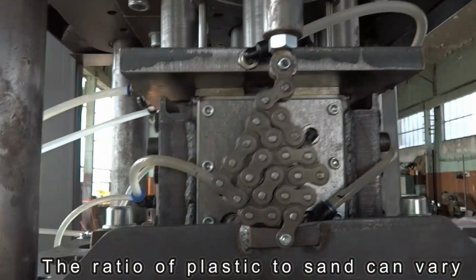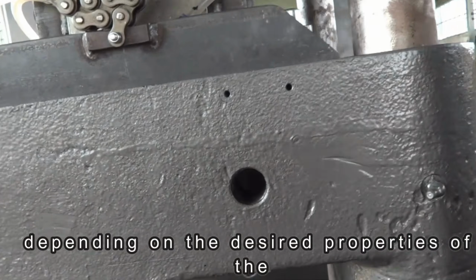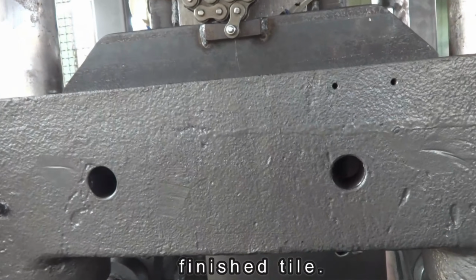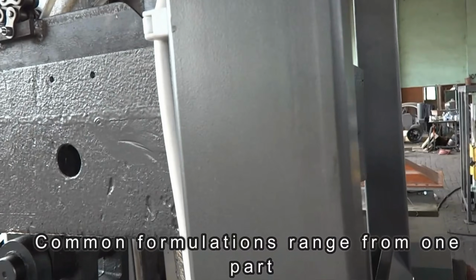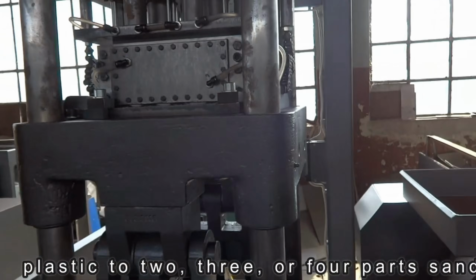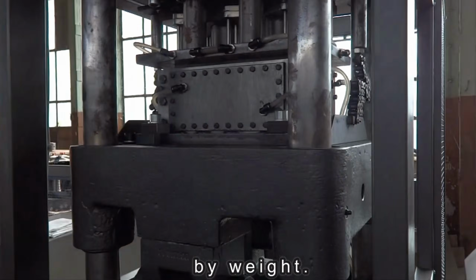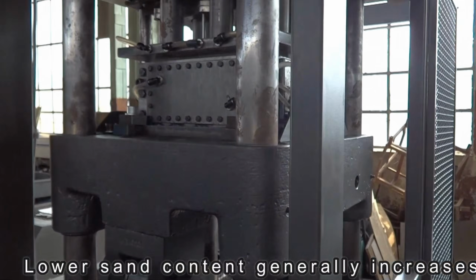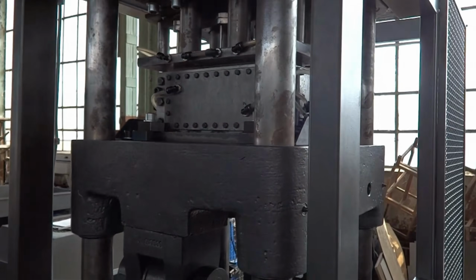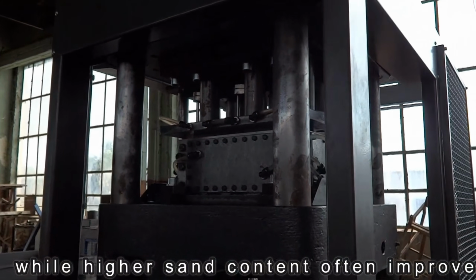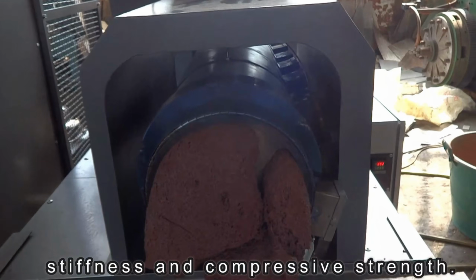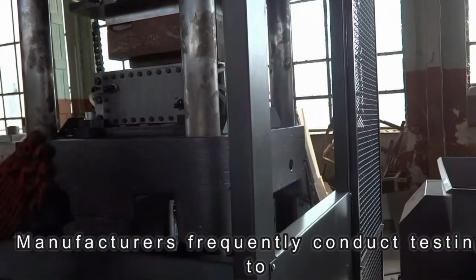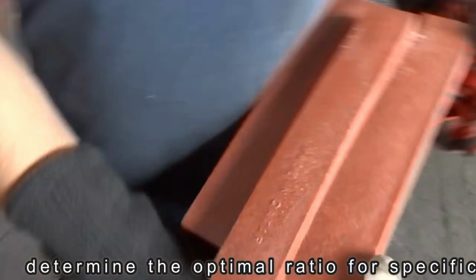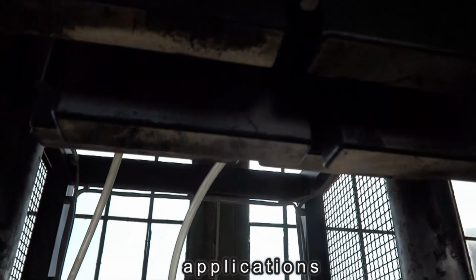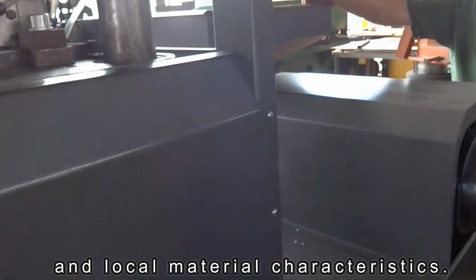The ratio of plastic to sand can vary depending on the desired properties of the finished tile. Common formulations range from 1 part plastic to 2, 3, or 4 parts sand by weight. Lower sand content generally increases flexibility, while higher sand content often improves stiffness and compressive strength. Manufacturers frequently conduct testing to determine the optimal ratio for specific applications and local material characteristics.